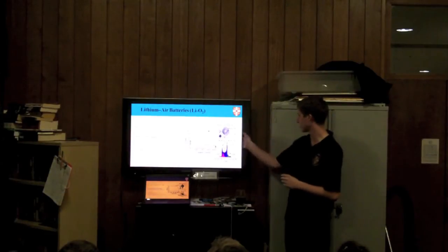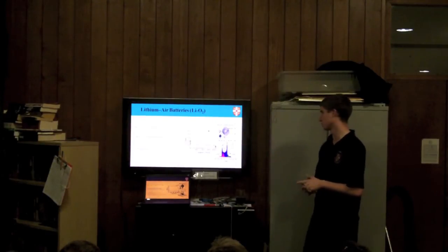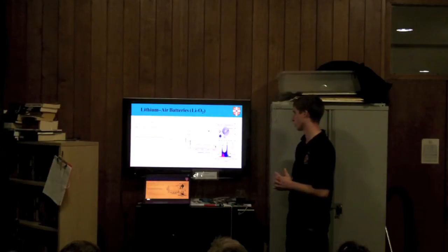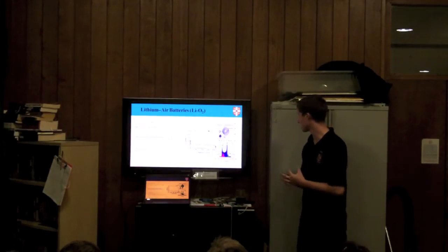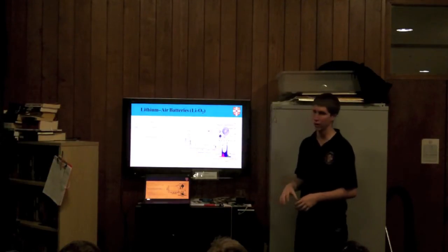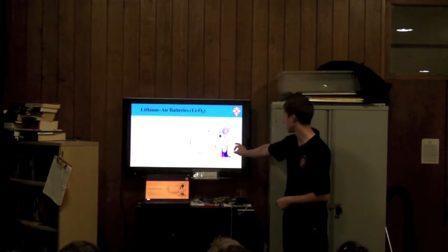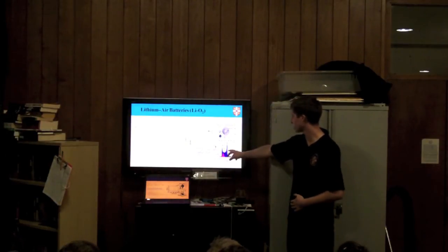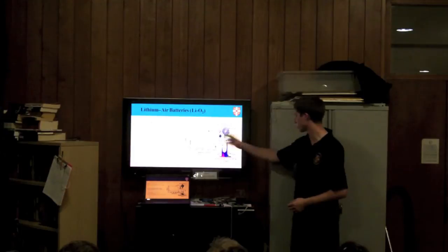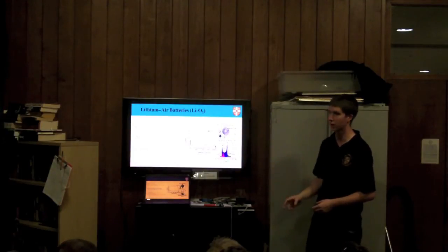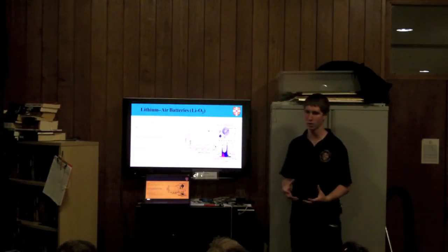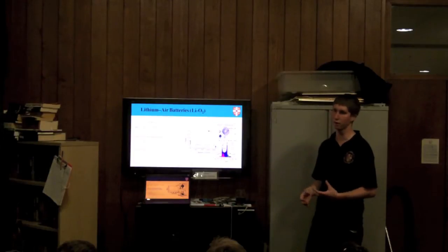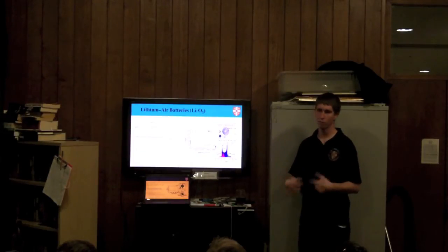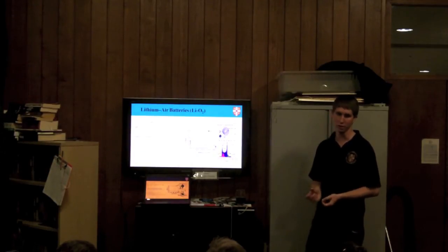This image stuff on the side, I wouldn't worry about too much, but this is the research that we're doing in our group with solid state NMR. It's just because we can see some of these side products that are happening. So besides the lithium peroxide, which is the blue plot, all these other colors represent things like lithium hydroxide, lithium carbonate, lithium formate, and all these other side products that we don't want to happen. And if all these form on one cycle, that's why after 10, the whole thing's dead, basically.